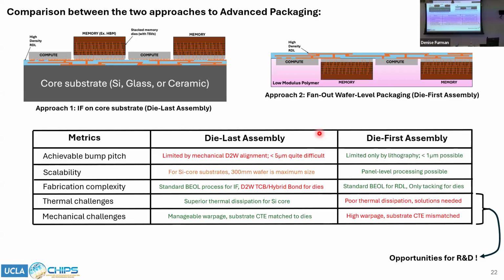In terms of scalability, if, for example, you use a silicon substrate, you can only go up to 300 millimeters, but the fan-out process has been demonstrated even at panel scale. And in terms of fabrication complexity, like I mentioned, die-last needs very complex die-to-wafer bonding, which requires a lot of process optimization, while in the die-first assembly, the fan-out process, you can just use standard back-end of line processing. However, there are some major challenges. In approach 1, the silicon substrate is very thermally conductive, so heat extraction is quite easy, and power delivery is also quite easy. And the substrate is the same material as the dies themselves, so they're CTE matched. Mechanically, this is more reliable, for example, in thermal cycling.